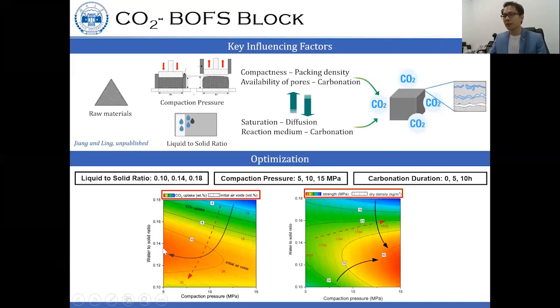And we found that the highest CO2 uptake doesn't necessarily have the highest compressive strength. So we can see the compressive strength achieved at the highest molding pressure is also somewhere around 0.125 or 0.13 water to solid ratio. As we can see, at this region we also could have quite high CO2 reactions or CO2 uptake.